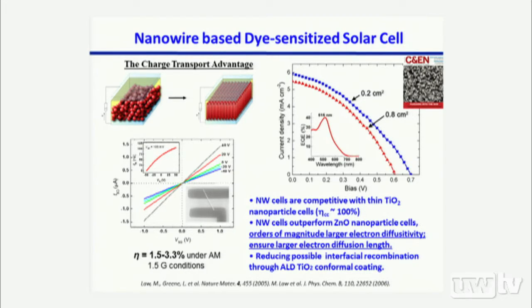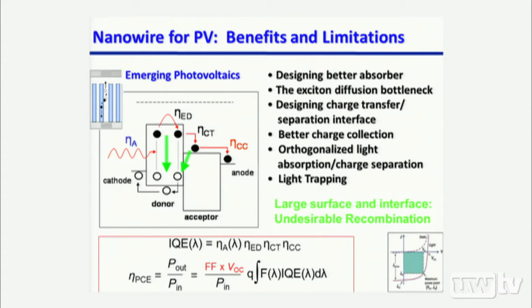Okay? And the major advantage of utilizing these single crystalline channels as electrodes is the enhancement of charge collection. If we measure the electron diffusivity within the single crystalline channel compared with nanoparticles, where the electron is percolating through the nanoparticles, the electron diffusivity in the single crystalline channel is an order of magnitude higher. Okay? So that's one of the advantages of utilizing semiconductor nanowire arrays as the electrodes in the solar cell. Now, if you look at many of these designs in terms of nanostructure solar cells, you can list many advantages. Let's say you can design a better light absorber. Okay? You can have much better electron diffusivity. You can design these interfaces to facilitate charge separation and charge transport, and you can introduce a light trapping phenomenon. There are many different advantages you can list.